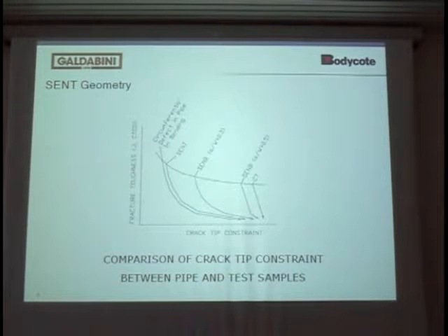This diagram is basically based on that developed by Nyhus and Thaulow. And what we've tried to show here is that when we're in the LEFM regime, we can very well characterise fracture by a single parameter, K, J, CTOD, and all our common geometries and structures will exhibit a fairly common toughness value.